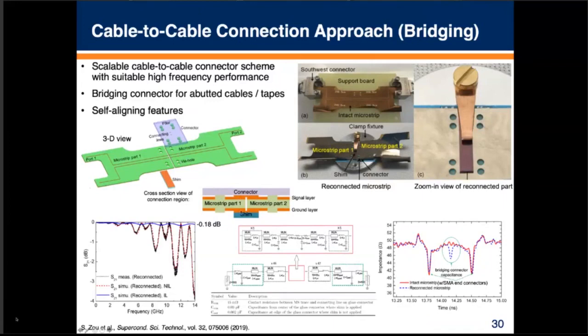And then a metallized portion on the bottom completes the ground. Here you can see a 3D blow-up view of it. Here is a structure cabled up and ready for testing. In this case, the student that did this decided to measure it in an intact method and then cut the exact same cable and do the connector attachment process, to use the exact same structures for before and after to see what the impact was of that connection approach.